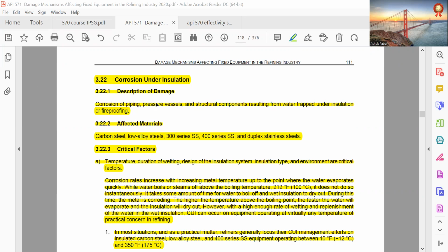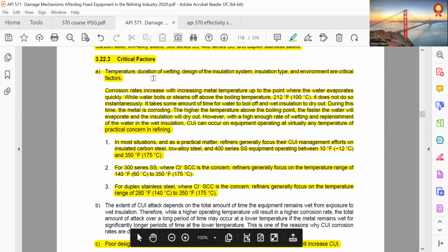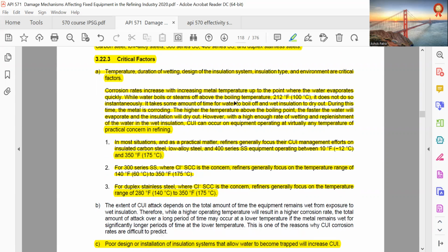Description of damage: corrosion of piping, pressure vessels, and structural components resulting from water trapped under insulation or fireproofing. Affected materials: carbon steel, low alloy steels, 300 series SS, 400 series SS, and duplex stainless steel. Critical factors: temperature, duration of wetting, design of insulation system, insulation type,